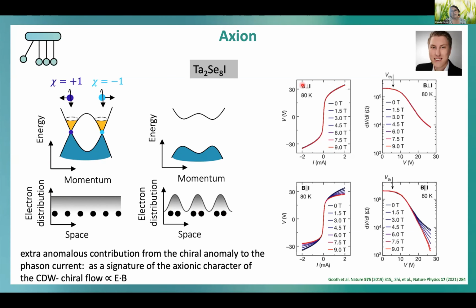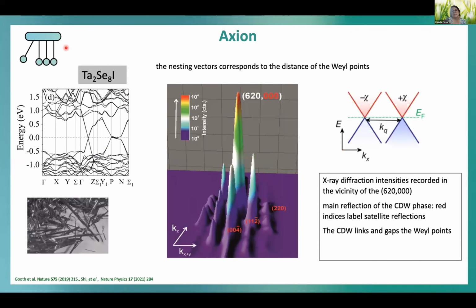And we did it again for magnetic field perpendicular to the current and for magnetic field parallel to the current. And indeed, you see an effect only in the case if the field is in the direction of the current, which was expected due to the chiral anomaly in the Weyl semimetal and the axion behavior. So the other important point was that the distance between the Weyl points should be exactly the nesting vector of the charge density waves. This was a little bit challenging to find out, but finally we also identified that this is exactly the case in this material.